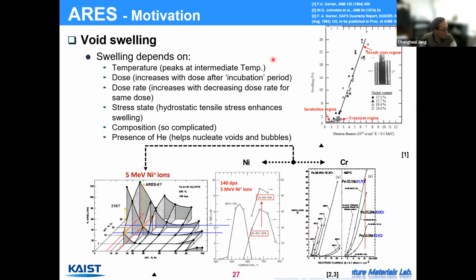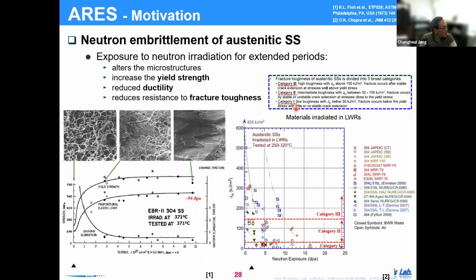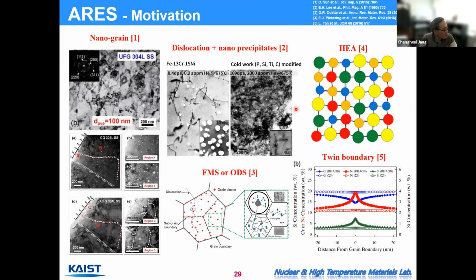So this is a mechanism of void swelling, but I think it's better to skip. There are several methods to reduce the swelling and the irradiation embrittlement. Neutron irradiation damage starts from the formation of vacancy and interstitial pairs because of the elastic scattering of nucleus. And then those vacancies move around and collect, combining together to form this kind of void. So the idea is, if you provide enough sink sites, like dislocations, grain boundaries and precipitates, those vacancies are trapped by those sites, and then they cannot form large voids. So that is the basic idea of irradiation resistant or swelling resistant material.